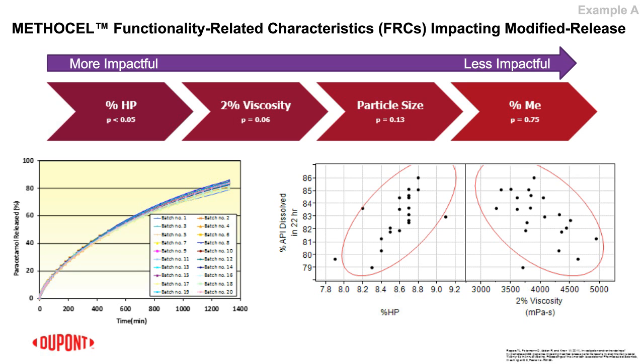Now, if you look towards the latter part of that 24-hour release profile, you start to see that those curves are fanning out apart from each other. And so we zeroed in on that, and we did some very simplistic linear modeling in JMP statistical software. And we found that there is a rank order, at least with this formulation and in this case, to those functionality-related characteristics. We found that hydroxypropyl substitution, for example, is a statistically significant factor dictating modified release performance. The molecular weight grade, or the 2% viscosity, is of borderline statistical significance. And then we found that particle size, all of these 20 batches met our CR-type particle size specifications, so in this case, that was a non-statistically significant factor, and methyl substitution was also a non-statistically significant factor, just because across those 20 batches, the methyl substitution was so tightly controlled.